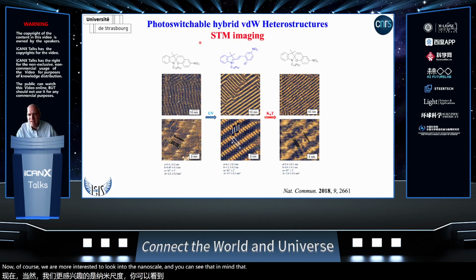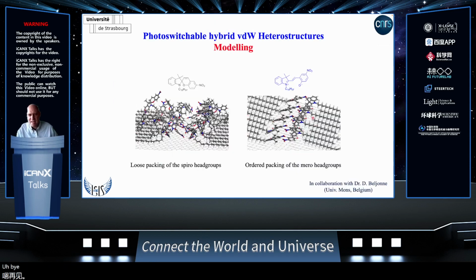Now, of course, we are more interested in looking at the nanoscale, and you can see that you can monitor by scanning tunneling microscopy, in situ in dry films, the isomerization from the spiro to the mero and back to the spiro. And actually, we can determine a unit cell that is reversible. You can see that the molecules are much better resolved in the case of the mero. And this has been demonstrated, the reason why, by David Beljonne in Mons, showing nicely that the head group of the mero packs flat onto the basal plane of the graphite or graphene, whereas the head groups of the spiro are more disorderly packed, and this gives some dynamics on the time scale of the STM imaging.